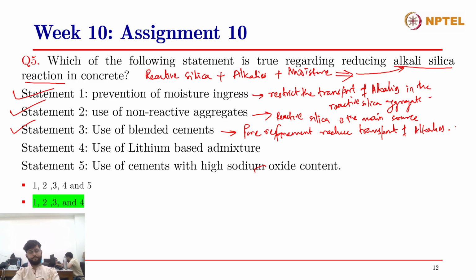One more essential component for alkali silica reaction to occur is the presence of calcium. If calcium is not present inside the concrete, then the precipitation of ASR gel is restricted. And in the case of blended cements, the amorphous silica present in these SCMs, meaning fly ash or slag or metakaolin or silica fume, reacts with the calcium hydroxide coming from the hydration reactions of the clinker.